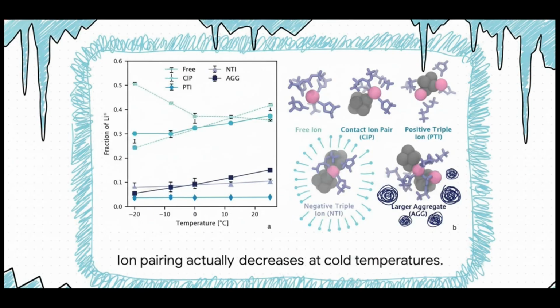But a rigorous molecular dynamics simulation proves otherwise. Look at the data here. As the temperature drops to -20°C, the fraction of free lithium ions actually increases, because the cold increases the solvent's dielectric constant. It actually helps keep those ions separated. So a lack of free ions? Not the culprit. The true bottleneck is something else entirely.